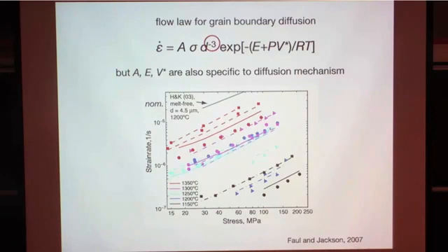The advantage is that we can determine the other parameters here, grain size dependence, stress dependence, this A, very precisely in the gas medium apparatus, because we don't have friction of the apparatus itself. In a solid medium apparatus, it's much more difficult to determine strain rates and stresses accurately because you have to account for friction. It's much harder to measure everything. Your samples get much smaller. The samples that we deform here are fairly large.